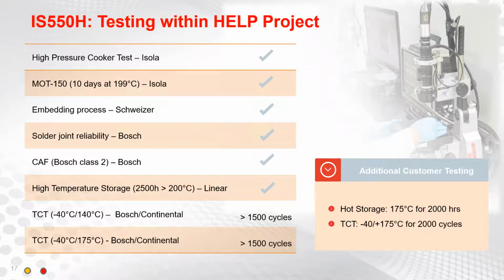So they started looking at things like high pressure cooker tests, higher maximum operating temperatures, embedded processing, solder joint reliability, extreme CAF testing, high temperature storage, and of course thermal cycling. A lot of these attributes were identified, and what they found out was a lot of the existing materials, like typical traditional epoxies or phenolic epoxies, just were not able to cut it, and they needed to work with someone to develop a new resin system, and that's where Isola came in.